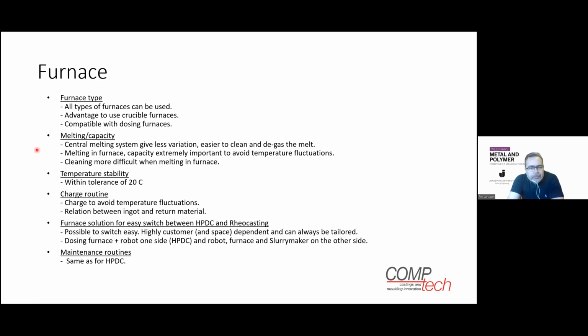We have seen that with a central melting system, we have less variation in temperatures. Temperature of the liquid part is in general very important. If we have central melting, it's easier to clean and degas the melt. It goes the same way with conventional high pressure die casting. If you're melting in the furnace by the machine, it's very important that you have enough capacity in the furnace, so you can avoid the temperature fluctuations. And then of course cleaning is more difficult when you melt at the die casting machine in the furnace.